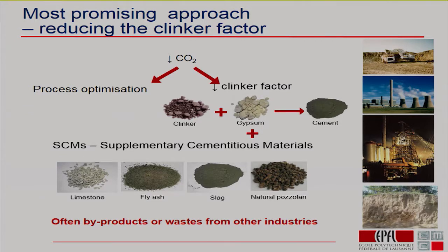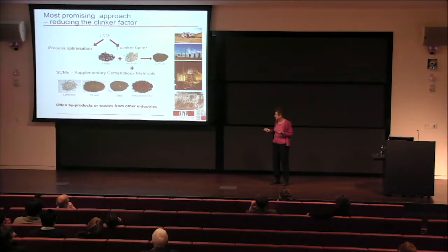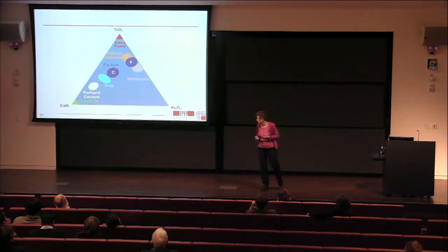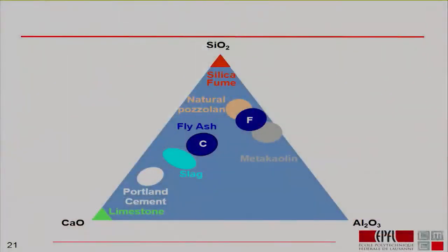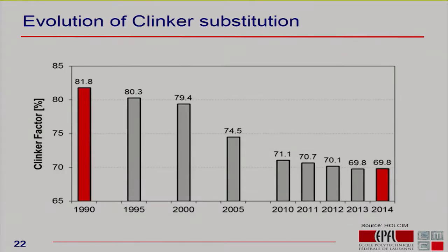And these things either have no CO2 associated, like limestone, because it's not heated up, it keeps hold of its CO2. Fly ash is a waste product, slag is a waste product, etc. These are basically CO2 neutral and therefore reduce the overall CO2. And incidentally, we can see that these all have quite similar chemistries. We can see here that they all tend to have the same ratio of silica to alumina, because that's what we find mainly in the Earth's crust, coming from feldspars and then clays.